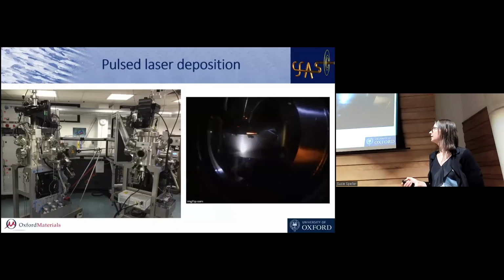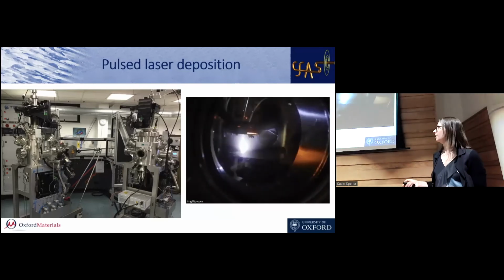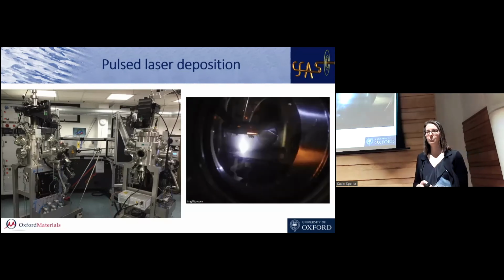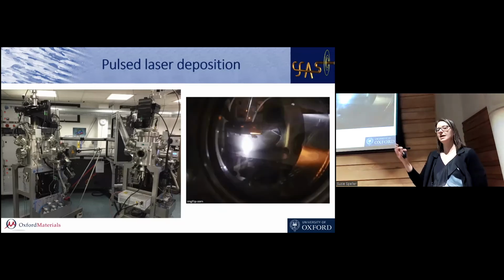Now, of course, we don't actually do it like that. What we do is use a machine that's a bit like this. This is the one in our lab. This is a pulsed laser deposition facility. It's got vacuum chambers where we do the deposition. It's got a big laser here. And what you do is you essentially have a solid piece of material of the thing that you want to deposit, and you hit it with a very high power laser and it vaporizes and the atoms get transferred onto the substrate that we're trying to grow it on.